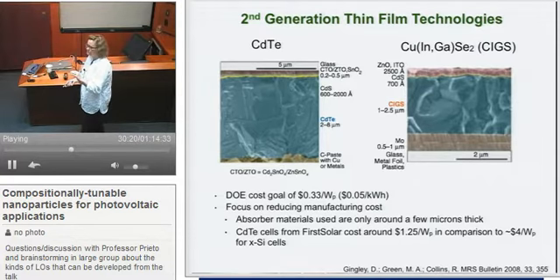But the current collectors, at least on one side, have to be transparent if you're going to get the sunlight in. So here you see a conductive transparent oxide down here, cadmium telluride, which is the main absorber layer in this case, p-type material, a thin layer of cadmium sulfide, and then we have our tin oxide, which is the current collector at the top. In this case, copper, indium, gallium sulfide, or selenide. Again, you only need 1 to 2.5 microns of it because it absorbs light really efficiently. In this case, molybdenum is the current collector on the bottom, and then indium doped tin oxide, which is a conductive transparent oxide on the top.